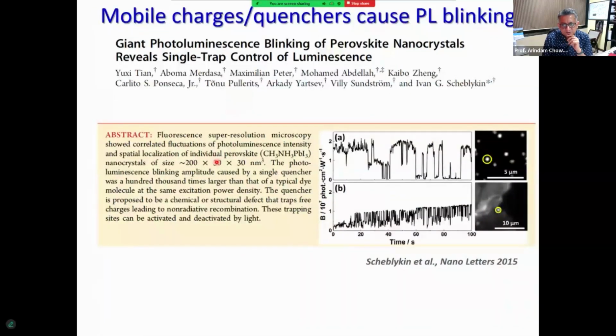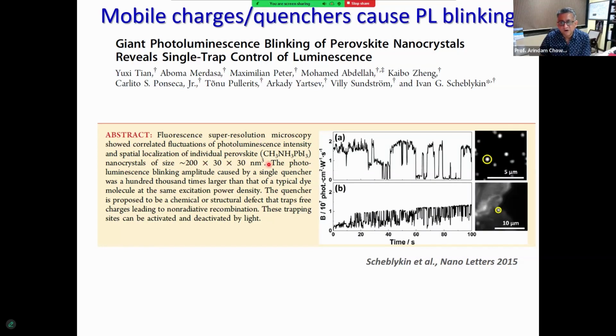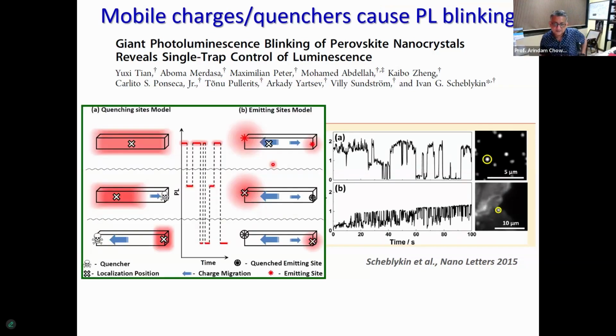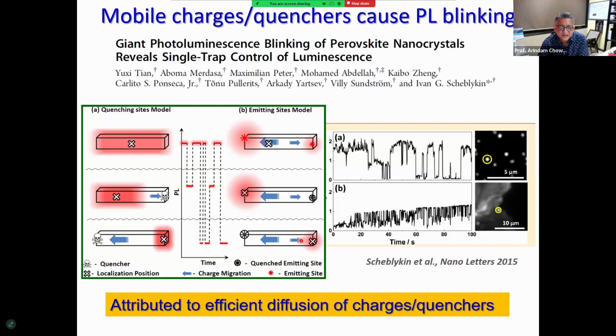Now, we were not the first people to observe blinking in nanocrystals of perovskites. In fact, Ivan Scheblykin's group from Lund University, Sweden, were looking at these 200 nanometer by 30 by 30 nanometer rods of perovskites, at these individual rods. And once they looked at them, they started seeing these huge jumps in blinks. They had a model, published in Nano Letters in 2015, and they attributed this phenomenon to migration of charges to some sort of a quenching site. A quencher is present, and this quencher essentially can appear or disappear. Without that kind of a behavior, there is no way you can explain why they would blink.